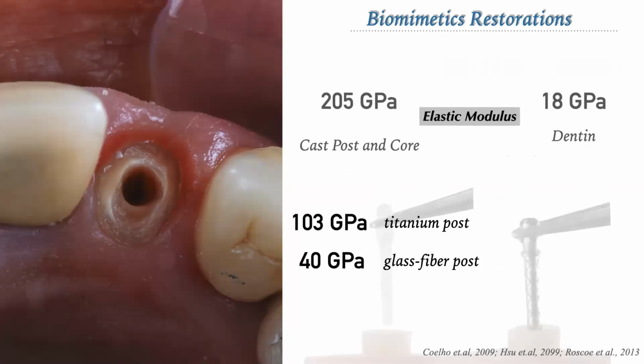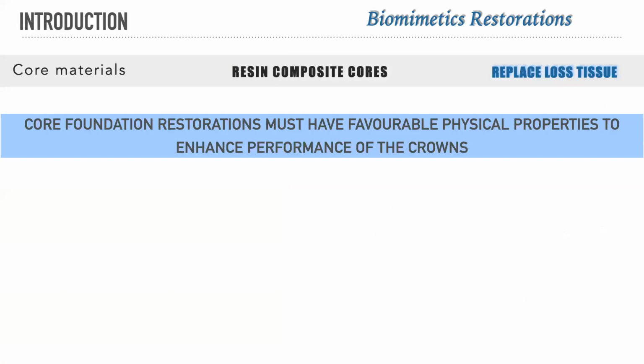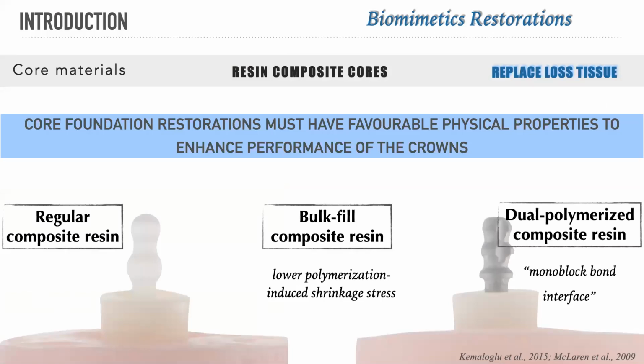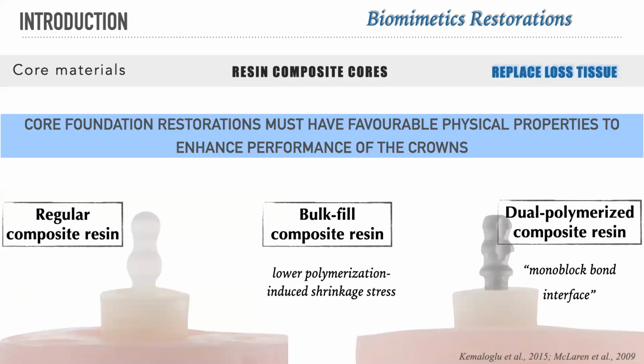So here we have the elastic modulus of cast post and core and the prefabricated posts. So the cast post and core have a very different elastic modulus compared to dentin. And we are trying to use a more biomimetic restoration, using materials that have the same elastic modulus as dentin. Core foundation restorations must have favorable physical properties to facilitate their resistance to masticatory forces and to enhance performance of the crowns. Composite resins are commonly used as material for core foundation restoration, and more recently, bulk fill composite resins have been introduced. And another alternative is the 2-in-1 material that is used to cement the post and build the core with the same dual polymerized material.